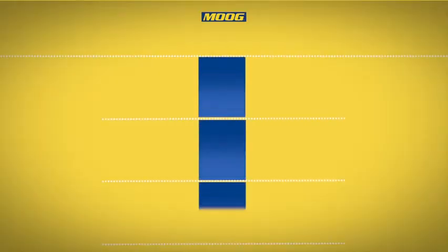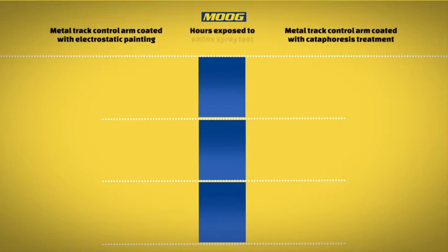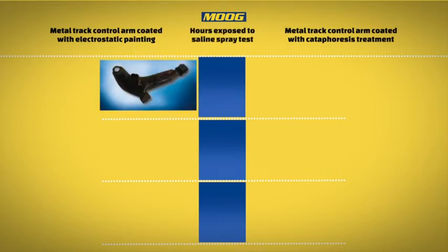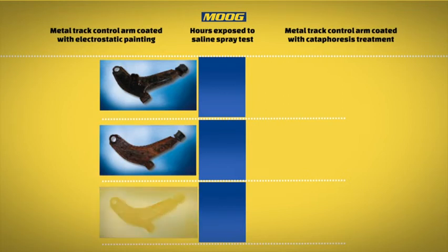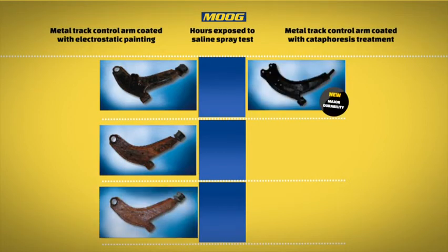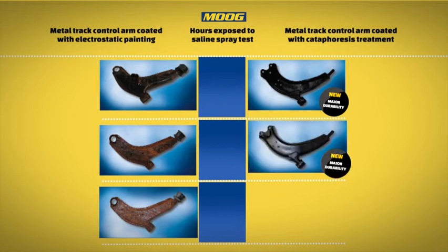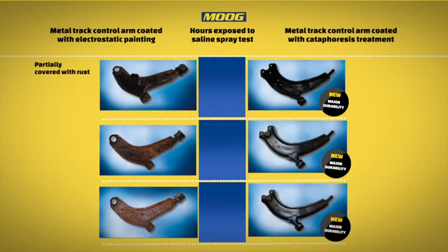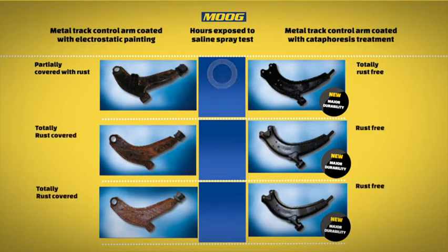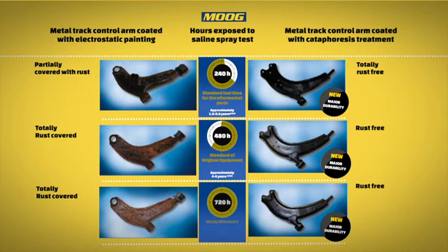It is important to note that cataphoresis painting was introduced by MOOG in 2011 for all the wishbone arms, as a change from the wet electrostatic painting process commonly used by most parts manufacturers in the aftermarket. Cataphoresis, on the other hand, is mainly used by original equipment manufacturers. In the electrostatic painting process, the part and the paint are subjected to different electrical polarity to ensure a better process of paint adhesion on the metal. In this case, the paint adheres to the small cavities on the external surface of the part more efficiently compared to the conventional wet paint process.